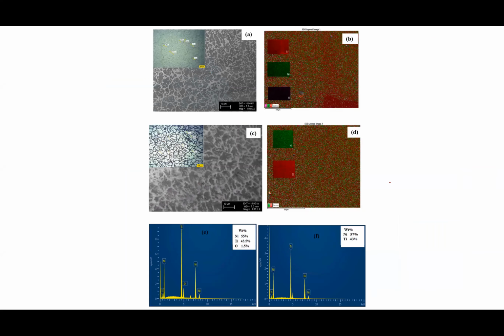This will give you a closer view of how the structures are being fabricated along the layers. Okay, so this is a closer view which depicts the VAM sample built with and without the laser marking. The columnar grains were formed on the samples built with and without laser marking. However, the sample without laser marking reveals a relatively coarser grain structure. The grain size ranges from 60 to 120 micrometer without laser mark, and 20 to 35 micrometer for marked samples.